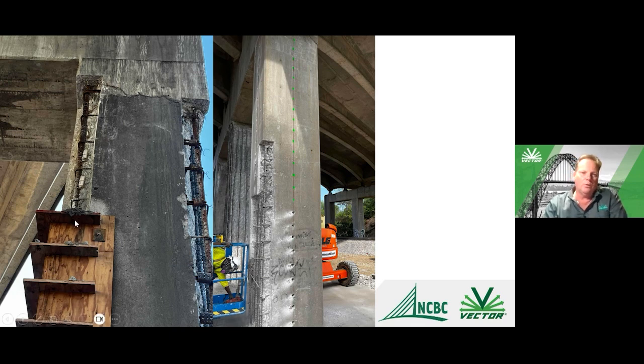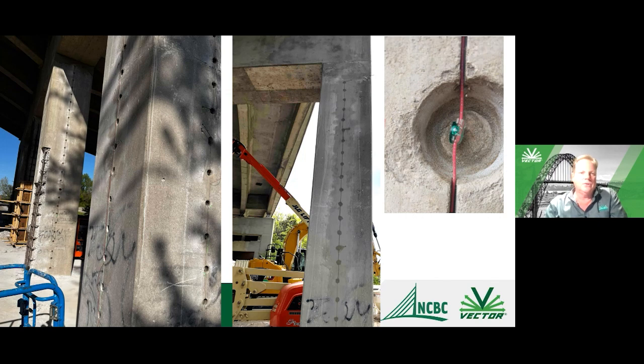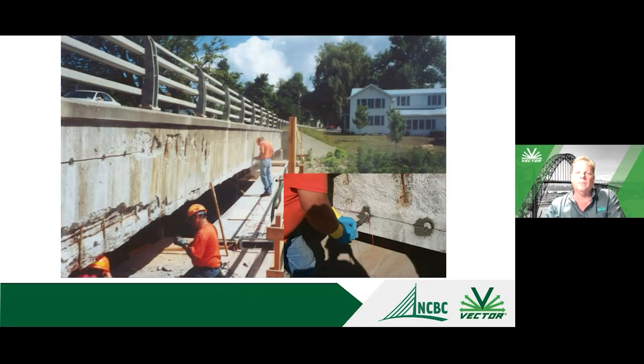So you see in these form and pour repairs, the type 1 anodes that are tied to the exposed steel. Then you see a series of the type 2 anodes that are being placed into the sound concrete to provide more holistic protection to the columns. And just a little more pictures in here. Here's these type 2 anodes that have been grouted in. You see the anode grouted into the core hole and an interconnecting wire, and these are all connected to the reinforcing steel as a galvanic anode system. So this is one way you can provide protection beyond the repair.